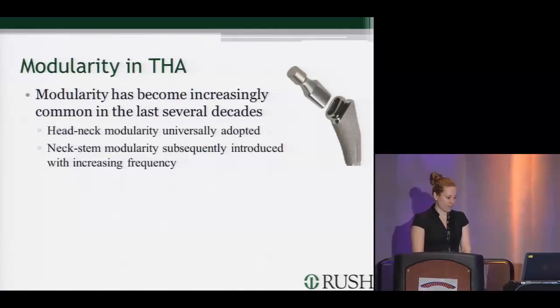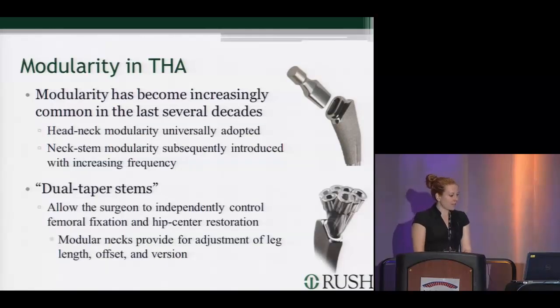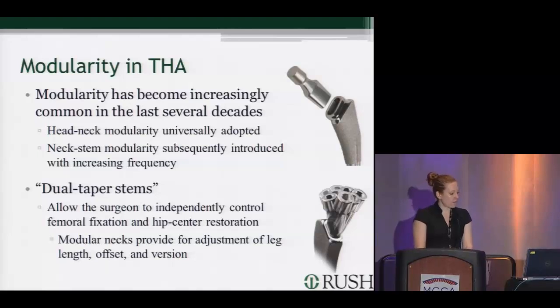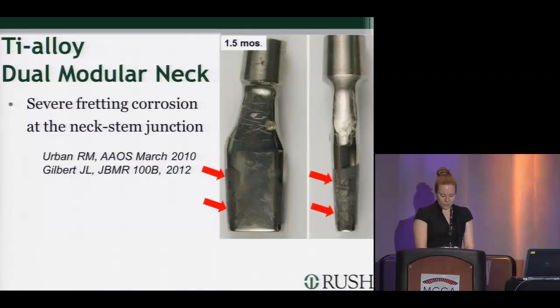Modularity in total hip arthroplasty has become increasingly common in the last several decades. Head neck modularity has become universally adopted, and neck stem modularity has subsequently been introduced with increasing frequency. So-called dual taper stems allow the surgeon to independently control femoral fixation and hip center restoration, as these modular necks provide for adjustment of leg length, offset, and version. Retrieval studies of titanium alloy dual modular necks have demonstrated severe fretting corrosion at the neck stem junction.